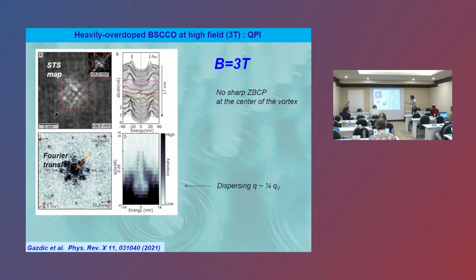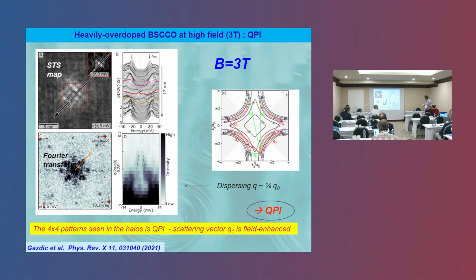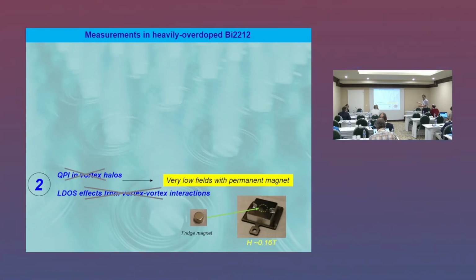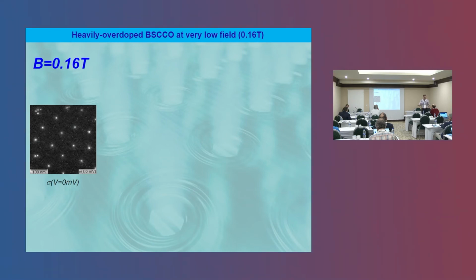And moreover, when you take the spectroscopy across the vortex core, again here there is no sign of the zero bias anomaly, and the presence of some subgap states are again detected. And the dispersion of this pattern, so at different energy, the period of this pattern varies, so there is a dispersion, meaning that these modulations are essentially due to quasiparticle interference or Friedel oscillation. So now, these were high field measurements. We know that the vortices interact with each other, so that the density of states of all individual cores might be affected by the presence of surrounding vortices.